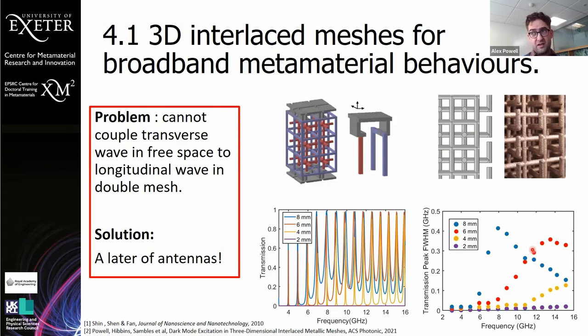this is such a wideband response in this metamaterial that what's limiting the bandwidth we can observe here is going to be the resonances of these antennas, because far away from resonances, it's not going to allow very good mode matching, and we get these extremely sharp Fabry-Perot resonances. And if you have any loss, these basically just vanish, and you can't see into the material far away from the antenna resonance. But we can see quite a lot doing that.